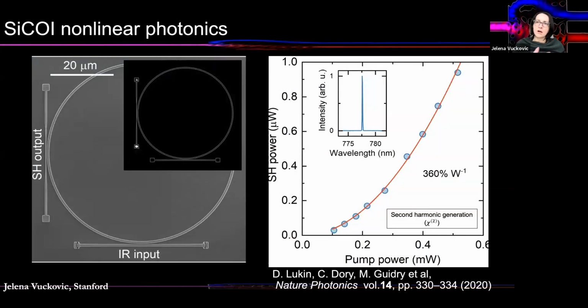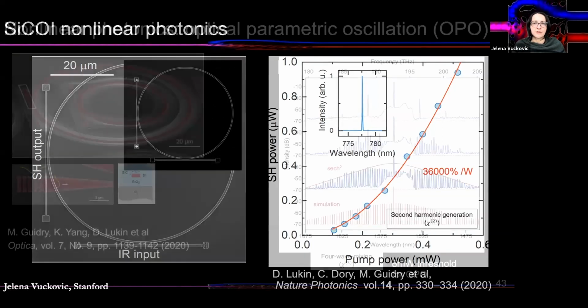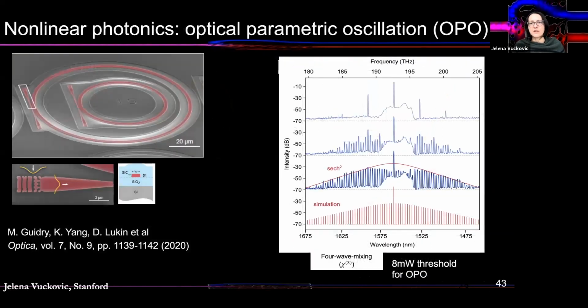In our first work, more than a year ago, we demonstrated second harmonic generation with efficiency of 360% per watt. Again, it's a second order nonlinear optical material. This should be updated. We're actually performing updated experiments, but we expect this to be around 36,000% per watt because of the improvement in Q factors that we have, which is already comparable with leading nonlinear optical materials. And we've also demonstrated optical parametric oscillation with low thresholds.